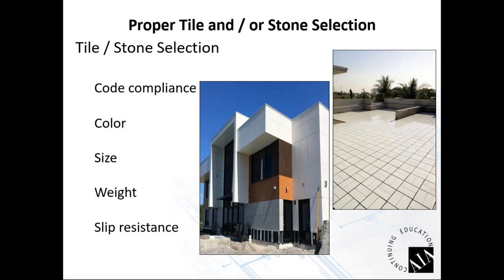Another thing that we take a look at as we go into the proper tile or stone selection is not only the code compliance of how we're going to install it, but also the color. I happened to be on a project a couple of years ago in Arizona, and it was summer, already into September, which is still quite hot. As we approached this building, they had used a darker granite on the exterior. And as you walked up closer to it, it felt like you were stepping into an oven. Temperature that day was probably about 100 degrees outside in the sun. The temperature coming off that building had to have been close to 140, 150 degrees.